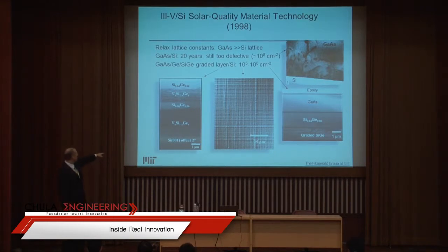So if you look at the left, these dark areas that you can't really see too well from the back there, those are massive areas of plastic relaxation, right? I'm creating zones where we're deforming this thing massively, and then at the top, we have very few threading dislocations coming up, right? A real amazing feat in terms of controlling plastic relaxation and then creating a very highly mismatched, high perfection material at the top surface.